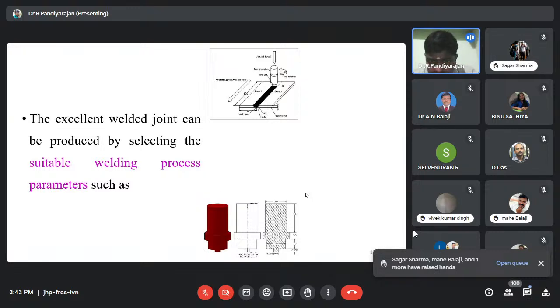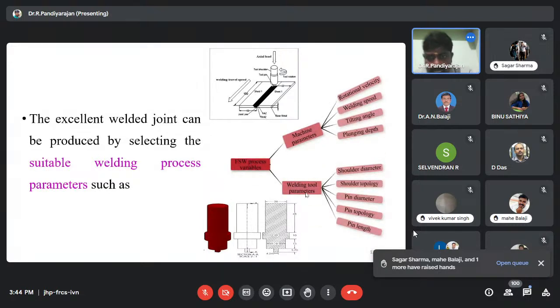The good quality of friction stir welding process is determined by 2 major parameters affecting the good weld quality. One is machining parameters. The machining parameters are tool rotational velocity, welding speed, tilting angle, and plunge depth. These are the major machining parameters that affect the weld quality. The next major influencing parameter is tool parameter. The tool parameters are shoulder diameter, shoulder topology, pin diameter and pin topology, and finally, the pin length. These are the major influencing parameters of friction stir welding process.